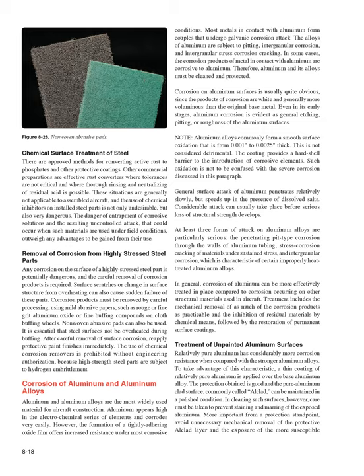General surface attack of aluminum penetrates relatively slowly, but speeds up in the presence of dissolved salts. Considerable attack can usually take place before serious loss of structural strength develops. At least three forms of attack on aluminum alloys are particularly serious: the penetrating pit-type corrosion through the walls of aluminum tubing, stress corrosion cracking of materials under sustained stress, and intergranular corrosion, which is characteristic of certain improperly heat-treated aluminum alloys. In general, corrosion of aluminum can be more effectively treated in place compared to corrosion occurring on other structural materials used in aircraft.